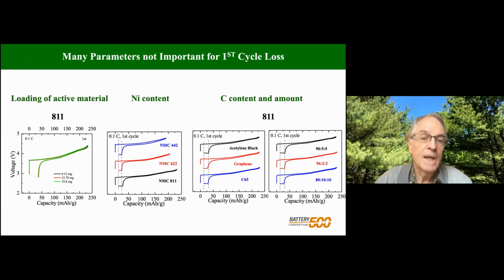The first cycle loss is independent of the loading of the active material. It is independent of the nickel content, so whether it's 40%, 60%, 80% doesn't make much difference. It's independent of the sort of carbon we used as the conductive material, and it's really independent of how much carbon and binder we use.